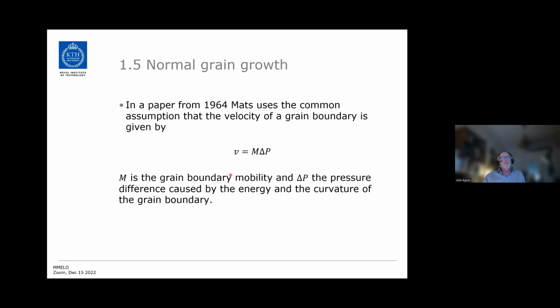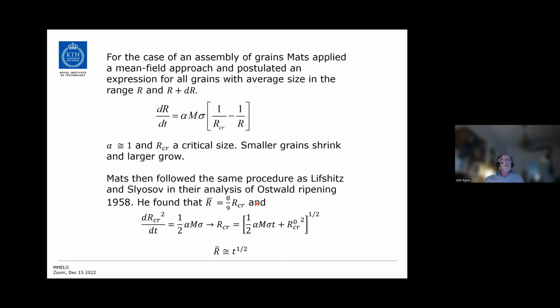In a paper from 1964, Mats uses a common assumption that the velocity of a grain boundary is a mobility times the driving force on the grain boundary. And this driving force comes from the pressure difference by the energy and the curvature of the grain boundary.